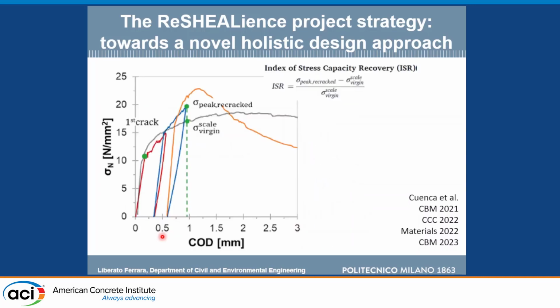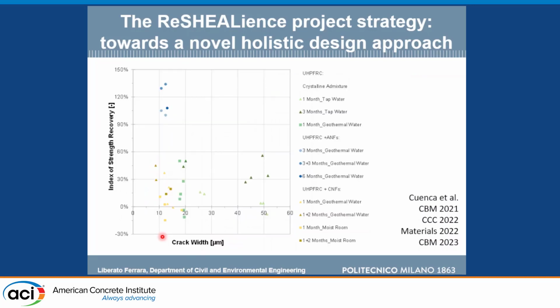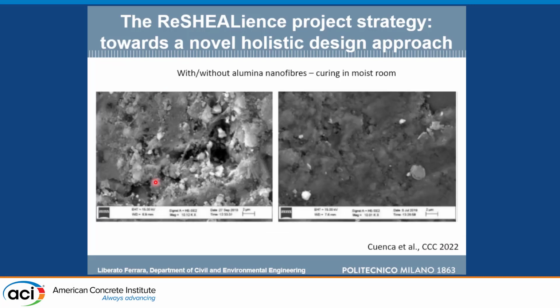Also for the capacity to retain the stress, which is an important design parameter, you see that alumina nanofibers are in the range of 100%, means that you completely healed and got back the same performance as for the virgin material. And some images here showing, you can see clearly here one alumina nanofiber crossing this crystalline structure which was formed.